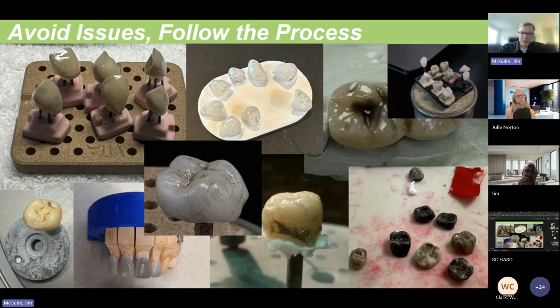What you want to avoid, though, is not following the rules, especially for zirconia. These are all customer pictures sent in to us saying, hey, my zirconia crown, my restorative work, comes out gray. It comes out with spots. One thing they all have in common is that they didn't use the proper firing schedule for the glaze they were using. And typically you want to rush things. And when you rush them and you don't allow the liquid from the glaze material to totally dissipate, to gas off, if your crowns enter the hot chamber too quickly, as the gases are boiling off, there is some carbon in there, and the carbon actually gets frozen when the glaze becomes too hot, and it doesn't let the carbon gas expel out correctly.